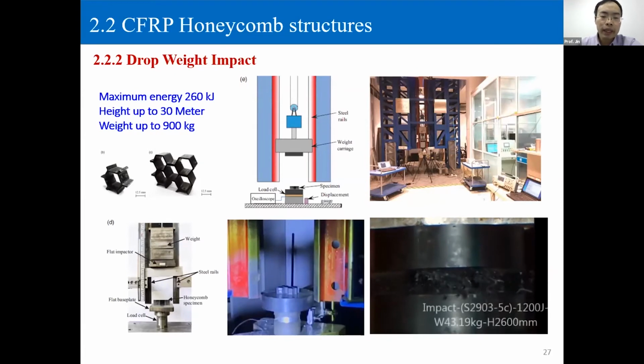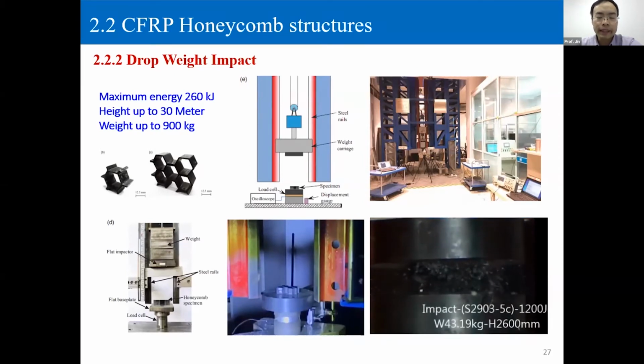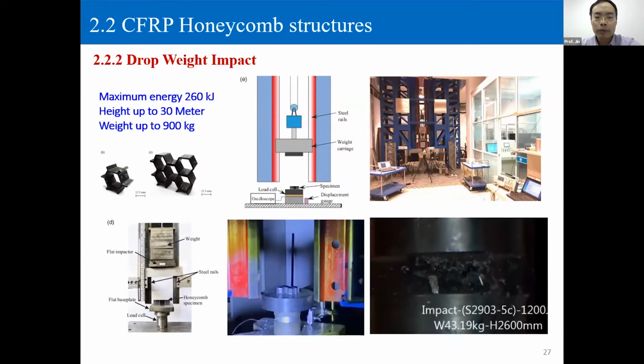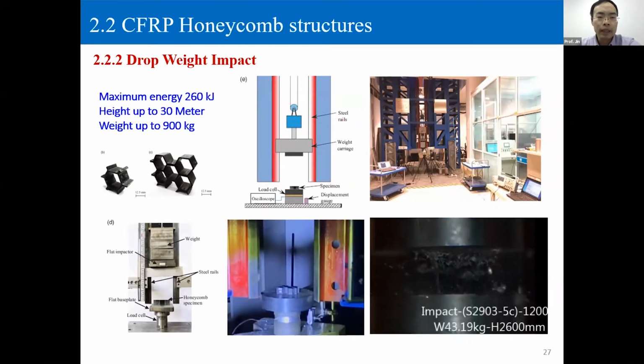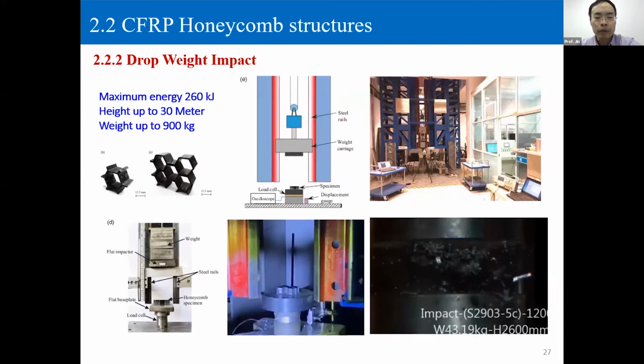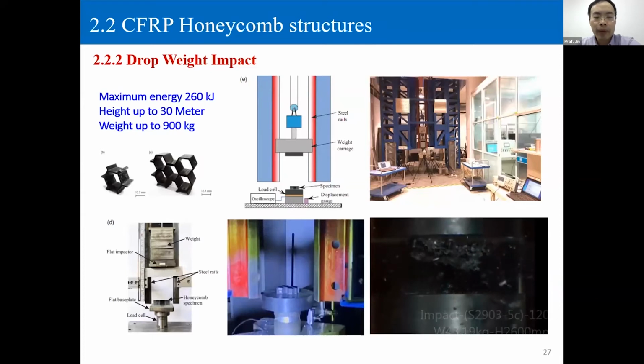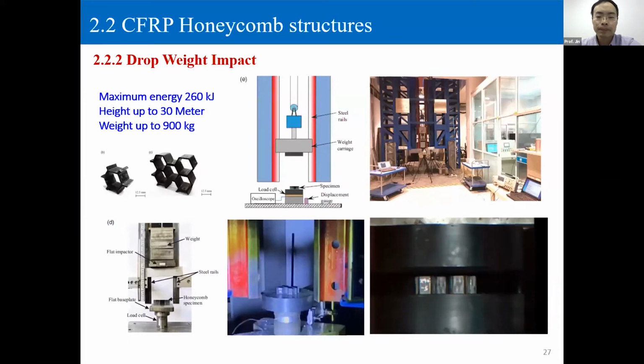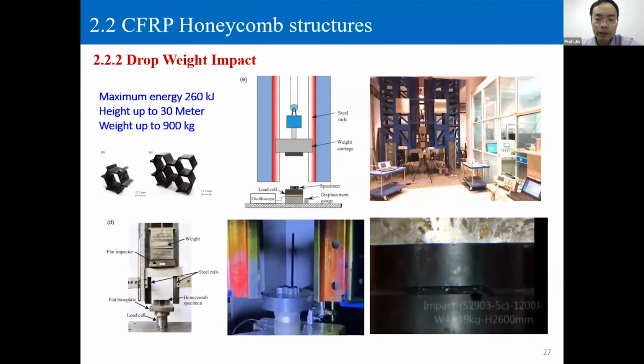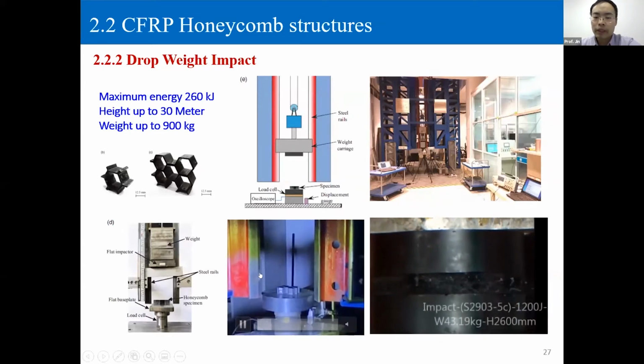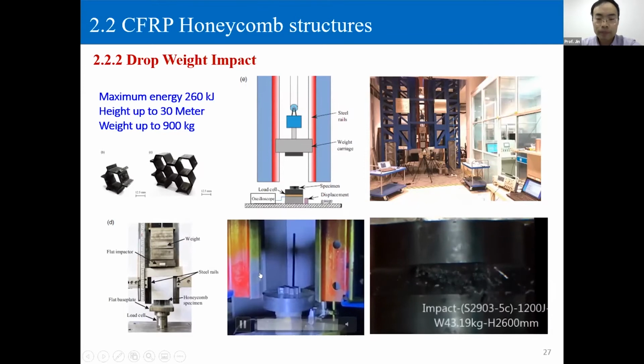Those honeycomb structures were tested using a drop weight hammer. This is the biggest drop weight hammer in China, with impact energy up to 260 kilojoule, velocity up to 20 meter per second, and maximum height up to 30 meter. So this video shows the low velocity impact on those structures.